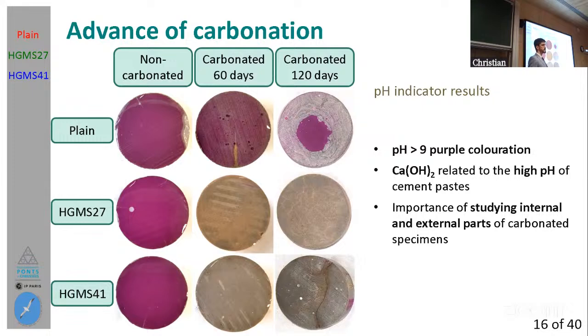Then, after 60 and 120 days of carbonation, for both cement paste with the spheres, we see this complete gray cross-section, which indicates that we don't have any high pH there, which is related to an important advancement of the carbonation in this cement paste. So that's something to take into account, and I discussed throughout my work that it could be related to the broken spheres that are increasing the interconnected porosity and affecting further this cement matrix due to the carbonation.